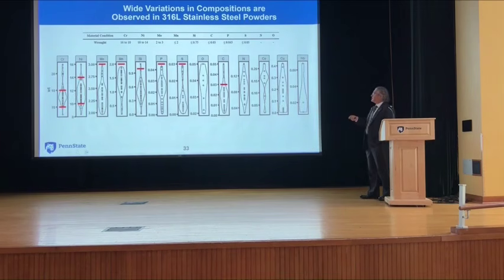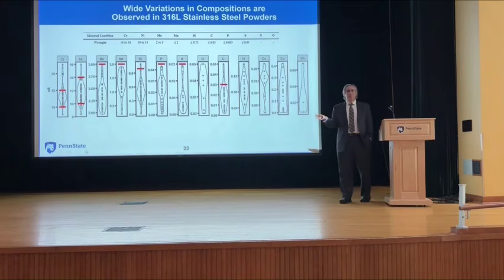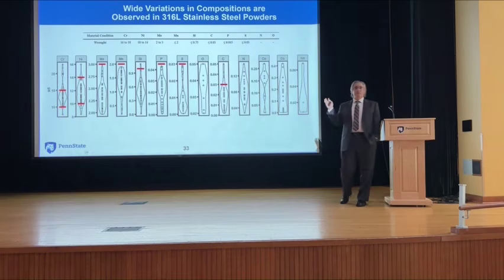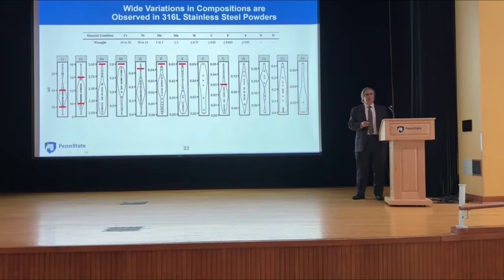So in this one, these give you variations in composition. I'll tell you, if you vary between 0.5 and 1.5 manganese in an austenitic stainless steel, you get 2 completely different alloys. They won't even behave. Their behavior will not even be close to similar. We've had issues with a nickel-based alloy 625, where we saw a 25% difference in yield strength because of a slight change in the iron content. So even within these allowable ranges, there's issues.